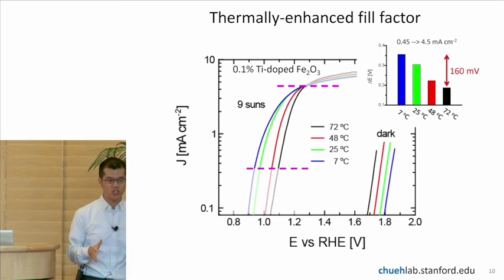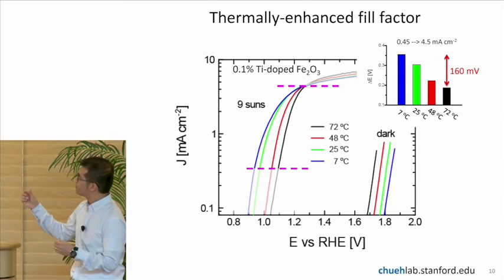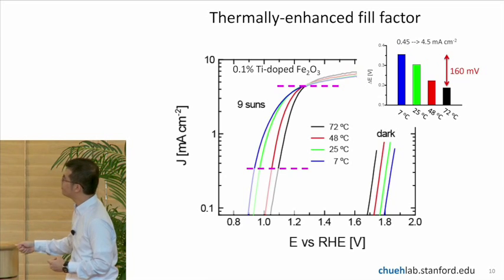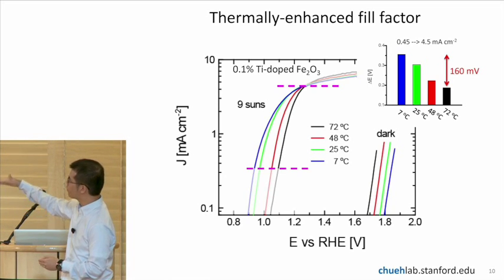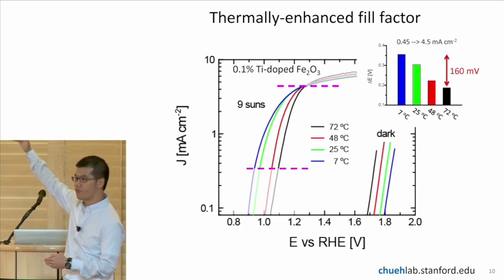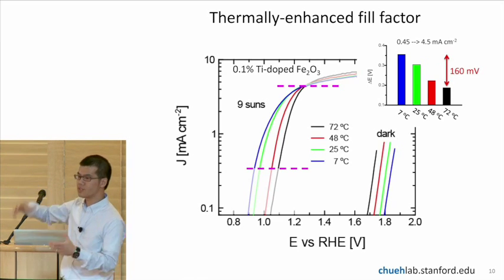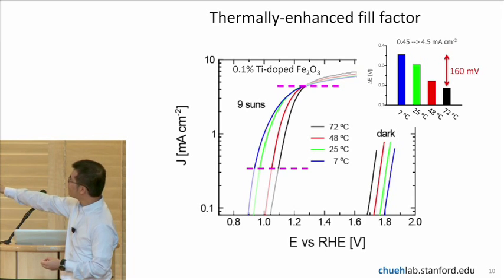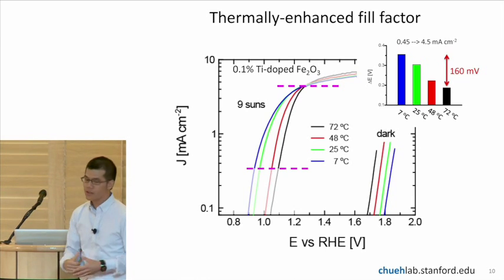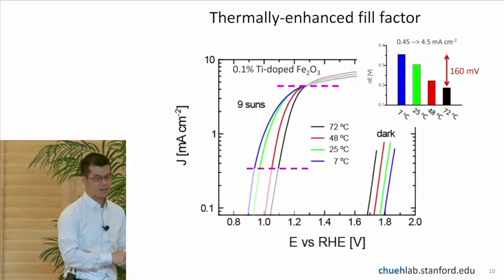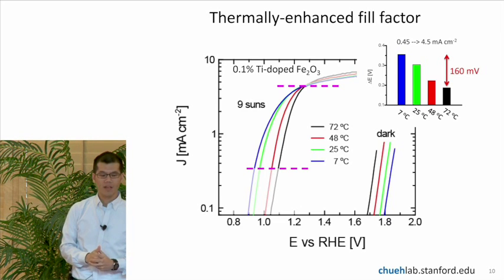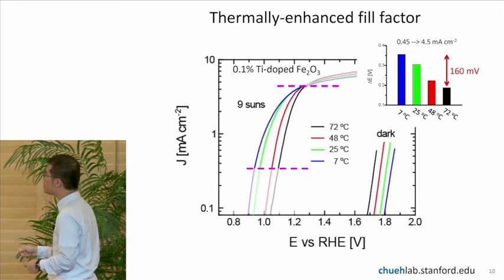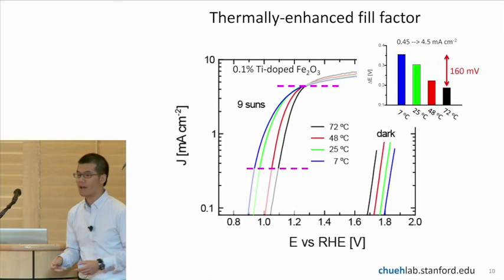So let me plot that. I'm basically showing you here the voltage difference needed to go between these two currents. So the voltage difference needed to go from 0.45 to 4.5 milliamps. So this is the extra voltage needed. At 7 degrees, you need to give about 300 millivolt in order to achieve a tenfold increase in the current.